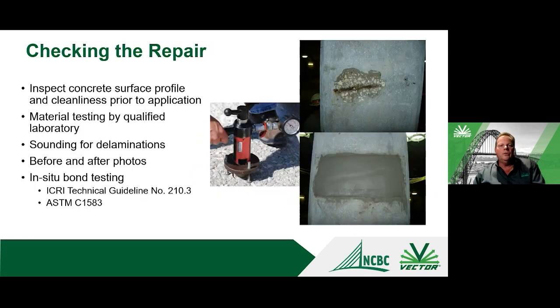And then what do we do if we want to check the repair? This is more along the lines of quality control. You're going to be doing a lot of documentation, like looking for delaminations and taking photographs. You can do the same thing as with concrete mix for new construction: you can do material testing of the repair material. But there are also some guidelines you can see listed here from ICRI or ASTM for direct bond testing.